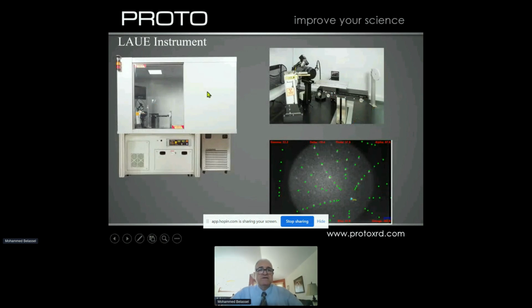Now, the instrument we use for these measurements is a Laue instrument, where we can place the blade inside on the platform, close the door, and start the measurement on the blade. This is a typical image we get, and here we show in green the overlay on top of the spots. This overlay is calculated, it is all theoretical, and we match this manually. We can do it automatically in some cases, but it depends on the image quality. Sometimes it's hard to do. And in this case, we are thinking of using some machine learning to improve the process.